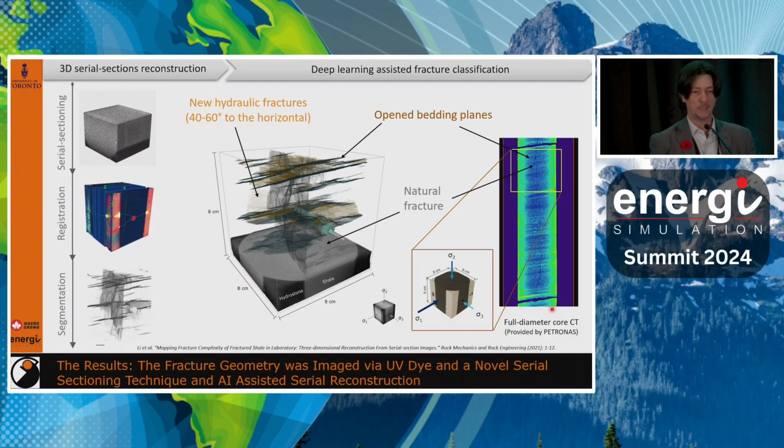The results were completely not what we would expect. We tried to X-ray CT scan the cube, but the resolution was not good enough. So we decided to grind the surface, cutting at very small intervals of 50 microns.